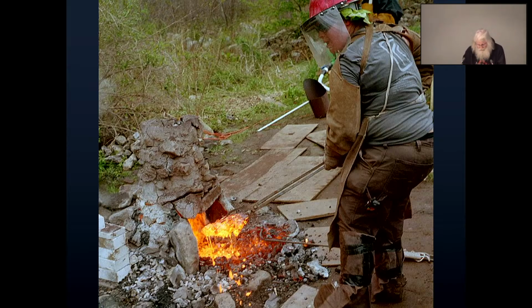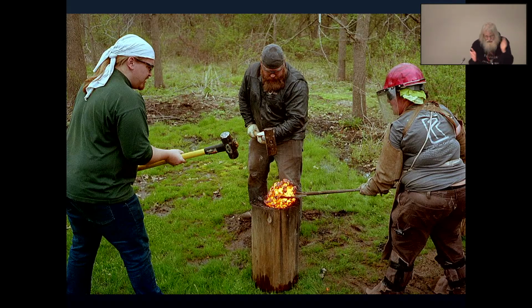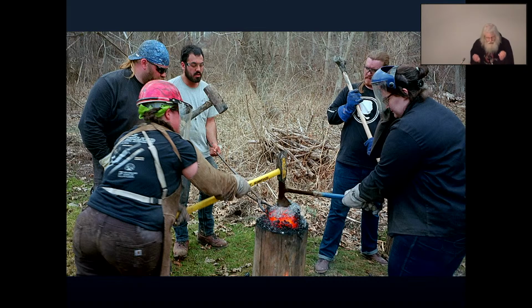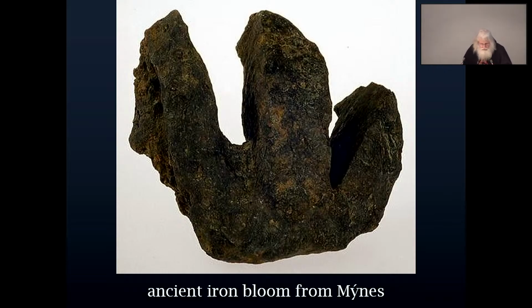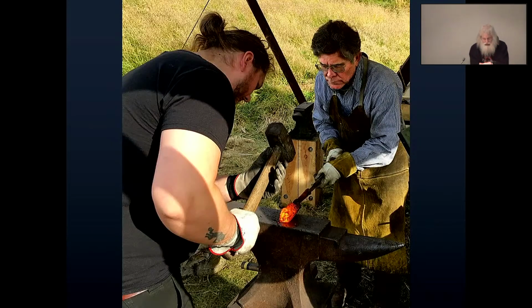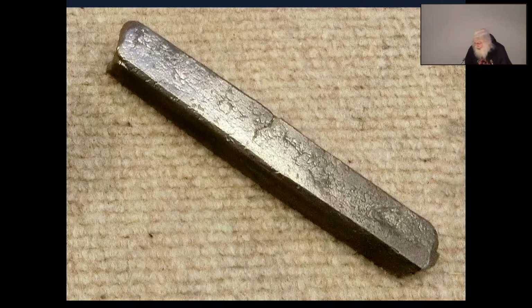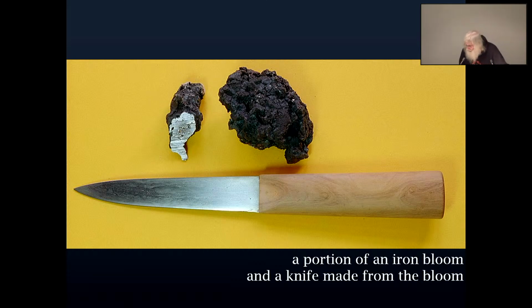Now, right away, the bloom is worked. It's hammered to try to squeeze it together into a more solid structure, to remove all these air spaces. In the Viking Age, there's evidence that the smith would use an axe to open up the bloom and look inside to see or test the quality of the iron. And we can see that in artifacts here in the museum, where the bloom has been split open to be tested. Now, when this bloom comes out, it's still not ready to be used for anything. The smith must take it and try to purify it, and he will fold it and hammer it, fold it and hammer it to try to push out some of the impurities. But when he is done, he has created an iron bar of nearly pure iron. And this bar can then be turned into useful tools and weapons.